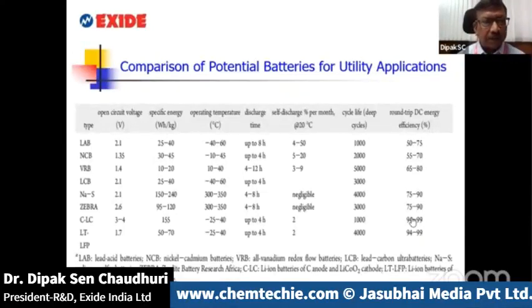And as you can see, lead acid has a very limited specific energy, not more than 25 to 40 watt hours per kg. Typically, maximum it can go up to 40 to 50 watt hour per kg. Some of the latest versions, you may have heard of the bipolar configuration, may take it to 60 to 70 watt hours per kg, whereas a lithium ion typically starts around 120, 130 watt hour per kg and can go up to as high as even close to 300 watt hours per kg.